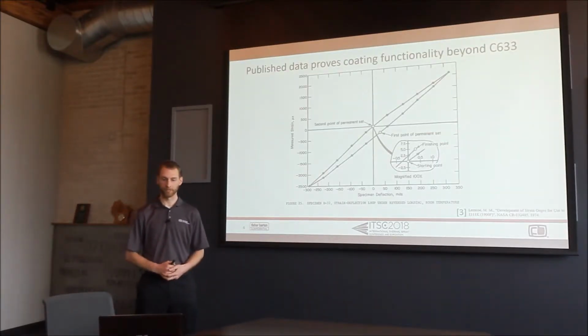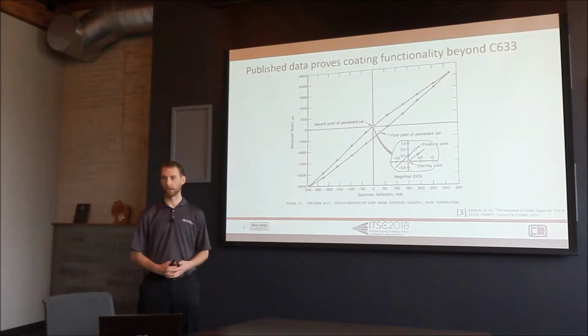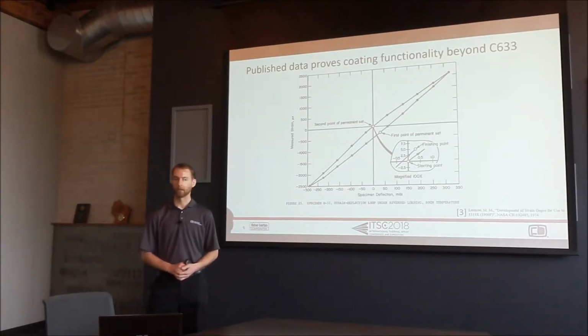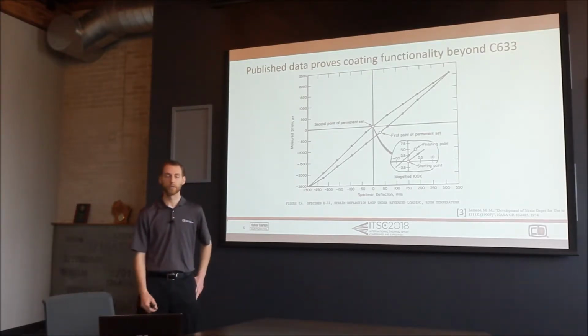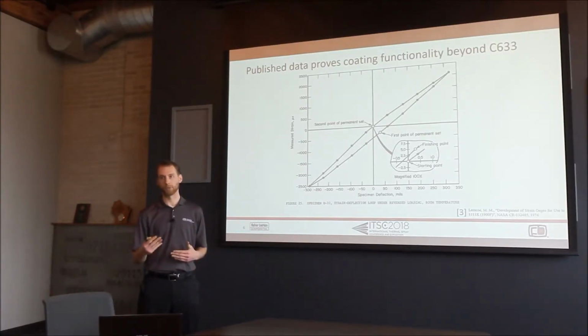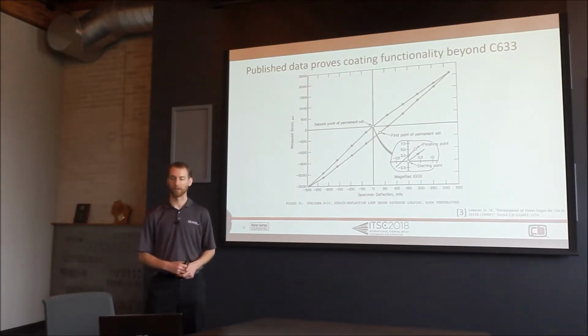As I mentioned, we've seen through literature already published data that does show that thermal spray coatings can function beyond the limits of C633. With C633, the adhesives that are used have limitations of about 10 to 13,000 psi. In some cases the coatings' adhesion lasts up to that adhesive strength, and so you really end up not knowing how strong that bond is.